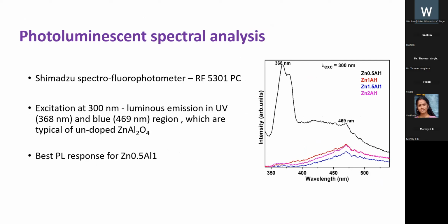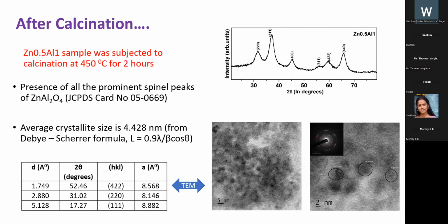Now coming to the photoluminescence analysis, we can see UV and blue emission at an excitation of 300 nanometer, which is a typical property of undoped zinc aluminate. The best photoluminescent response is observed for the sample with the less zinc content. And this also substantiates the structural analysis, XRD and FTIR.